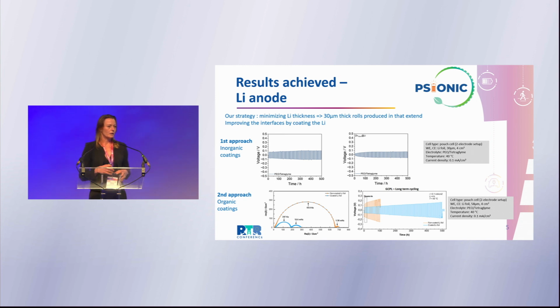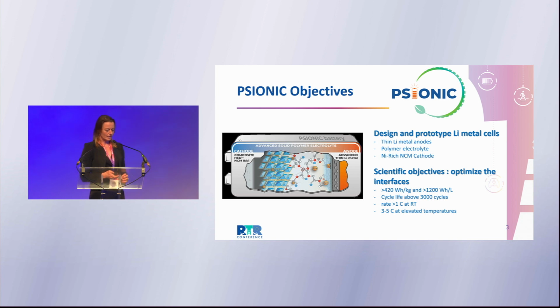Maybe quickly, what we will develop in the project will be done in two times. If I come back to this slide, maybe it will be easier. So we will progressively move to these high KPIs. So progressively we will improve all the different components. First, working on, let's say, not optimized lithium, not optimized cathode, and not optimized electrolyte, and progressively re-inject the improvements to thinner the lithium, to thinner the electrolyte, to have a better conductivity, and to increase the energy density of the positive electrode.